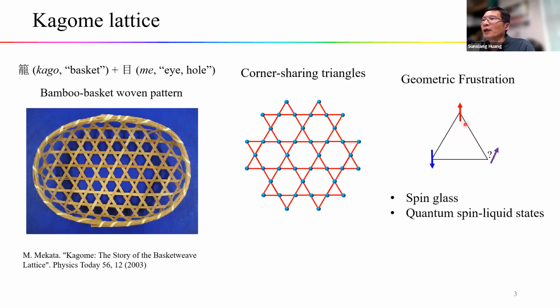In spin systems, this triangle geometry could induce geometric frustration. For example, in these antiferromagnetic coupling systems, these 2 spins are aligned antiparallel. So the third spin in this corner is frustrated because it doesn't know which orientation it should take, because for either up or down, the system has the same energy. So in many of these Kagome magnets, there are spin glass states and possible quantum spin liquid states.